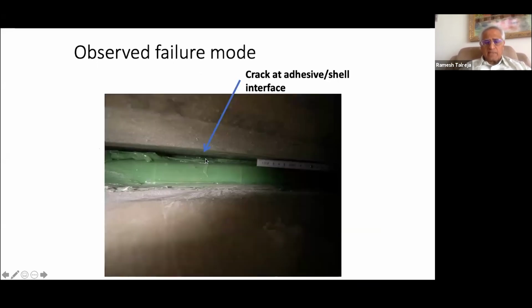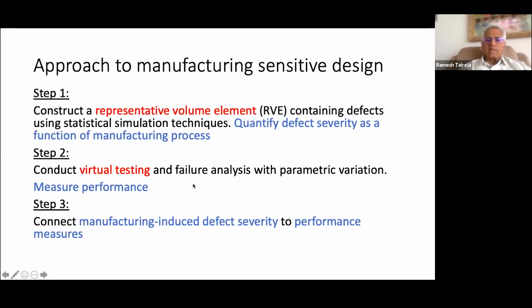And you see the result of that is that between the outer shell and the adhesive that joins the lower shell is quite irregular. The clumps here and so on, missing adhesive here. So defects are a part of real life in composite materials for the most part. In very few exceptional cases where the cost is not of much concern, you can control the process completely and avoid defects. So in this manufacturing sensitive design that I would describe to you, there are three essential steps.